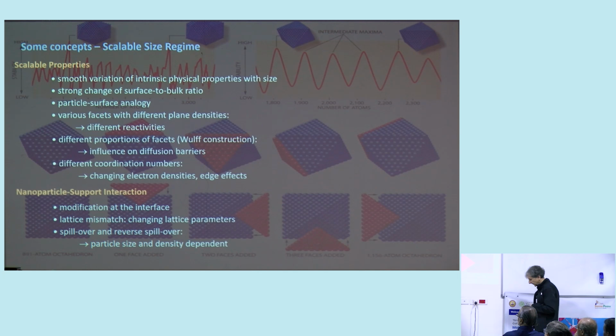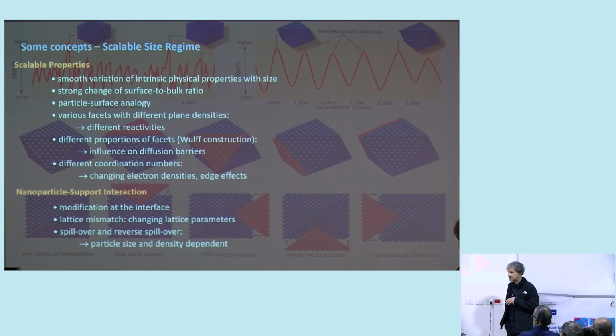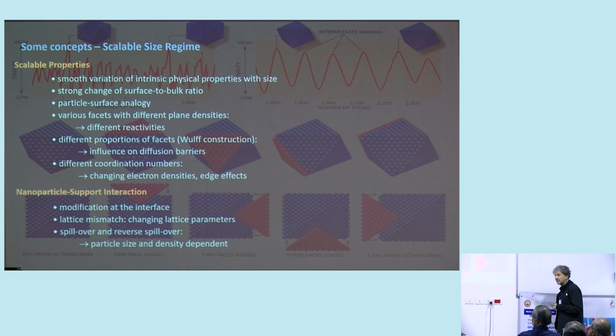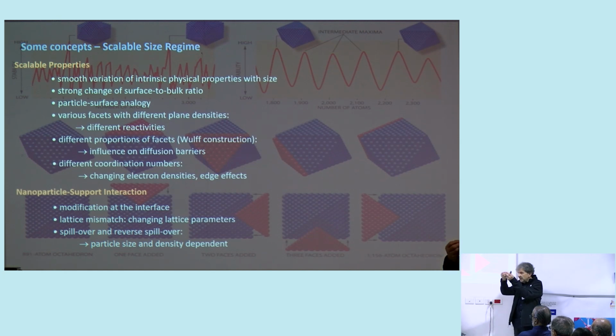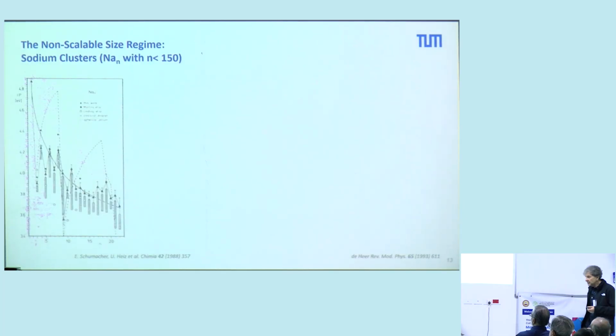But there are also properties that are dependent on the particle support interaction, because in heterogeneous catalysis, you put these particles on a surface. And so you have a modification at the interface which can influence the catalytic properties. You can also have a lattice mismatch with the underlying support, and you can change a little bit the structure of these particles, but this will not be very drastic. And then, of course, you also have spillover and reverse spillover. Intermediates on the particles can diffuse on the surface and do a reaction on the surface, or just the opposite. But now let's have a look at the non-scalable size regime.